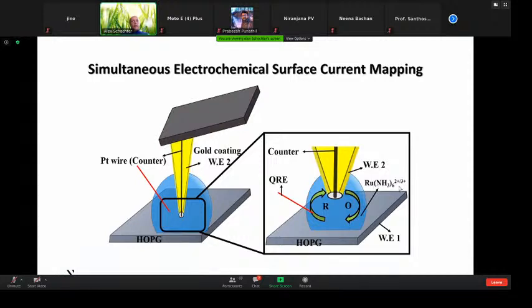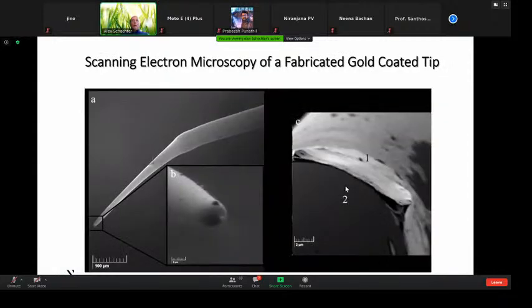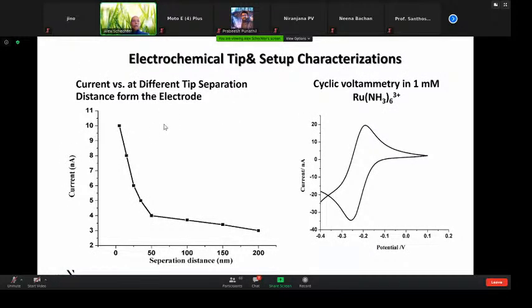First we calibrated it with the ruthenium salt, and then here's the image of the gold coating over the tip after it breaks down. Okay, this is the cantilever, and we measured. This is the ruthenium, and one of the things that we wanted to see is what happens if we approach the surface. So here, this is what we call the tip approach. We took the tip and we put it closer and closer to the surface. And you can see as you go very close to the surface, 50 nanometers and below, the current suddenly jumps to very high current.